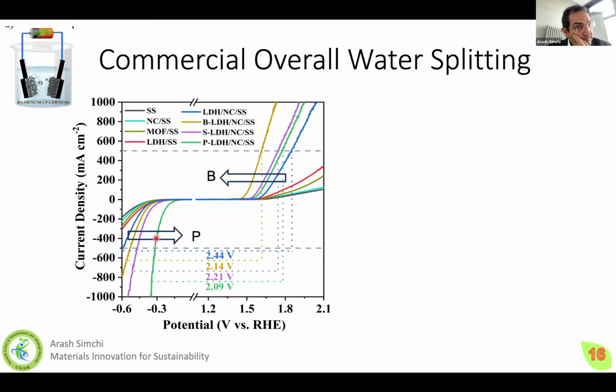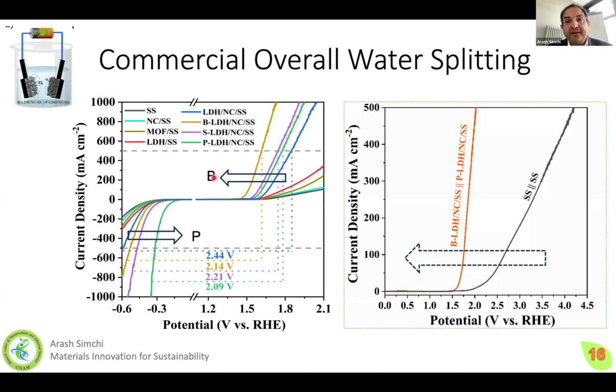We have found that phosphorus and boron influence the efficiency quite well, significantly decreasing the overpotential and reaction kinetics. And then we made an overall water splitting system, as you see here, current density, and this is potential. This is our base electrode, which I showed you, and this is the electrode modified by the sustainable ceramic materials which exist in nature. However, I just changed the anions and cations inside the lattice by electrochemical methods in replacement reactions. And you see the difference, how much the difference is.